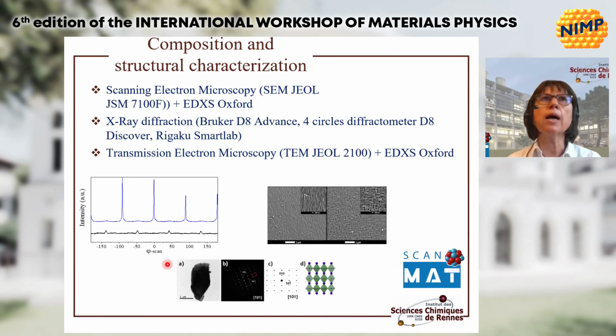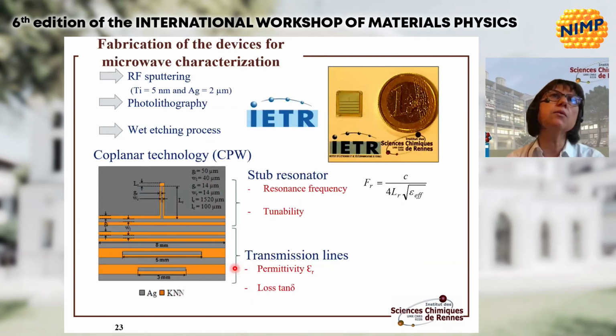Thin films have been characterized by scanning electron microscopy, standard, with only one electron beam, X-ray diffraction, theta-to-theta with a four-circle diffractometer, and also transmission electron microscopy with EDX. For dielectric characterization and device measurements, metallization has been performed with 5 nanometers of titanium, then 2 microns of silver, with standard photolithography and a wet etching process.